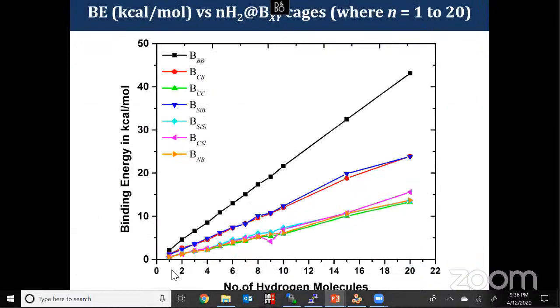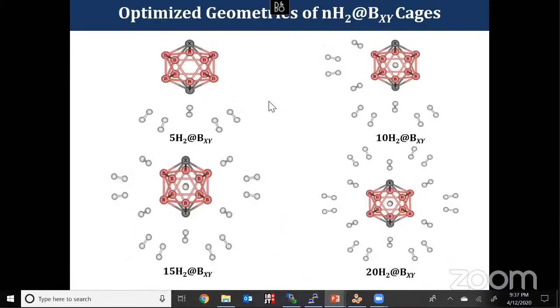So this is the binding energy graph. You can clearly see that the B12H12 2- cluster has higher binding energy than the substituted ones, the mono-substituted has the next higher binding energy after 2-, and the neutral cluster has lesser binding energy. One more interesting thing here is that all the hydrogen molecules prefer end-on overlapping. That means head-on overlapping, that means only one hydrogen atom points towards the center of the boron cage.